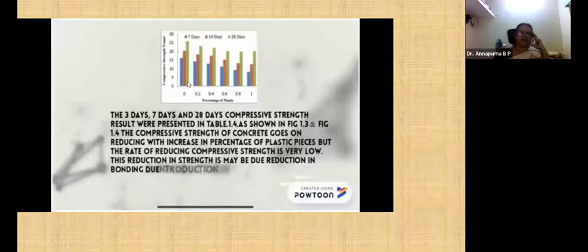with the increase in percentage of plastic pieces, the compressive strength reduces, but the reduction is very small compared to conventional concrete. This is because of the reduced bonding between the concrete materials. So it creates a lighter weight mix. A standard weight concrete weighs 145 pounds, whereas these plastic blocks weigh 90 pounds.